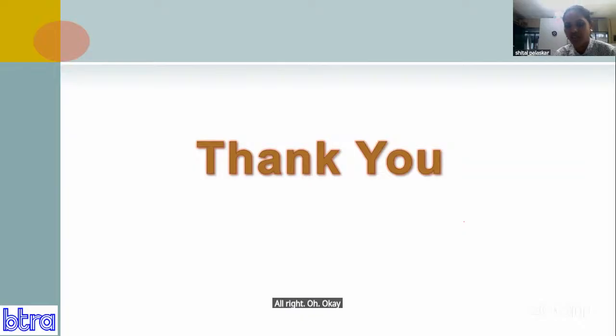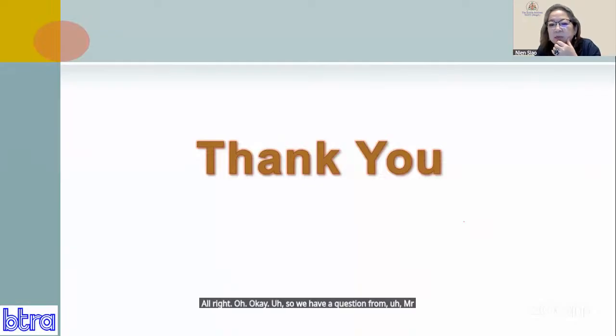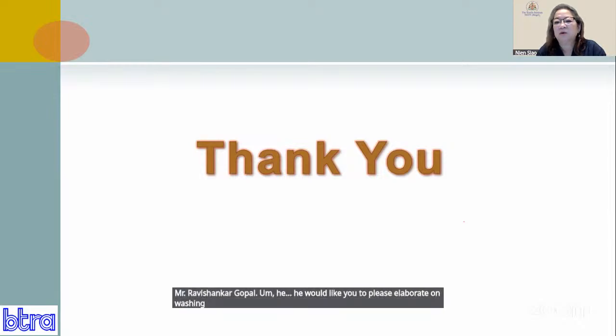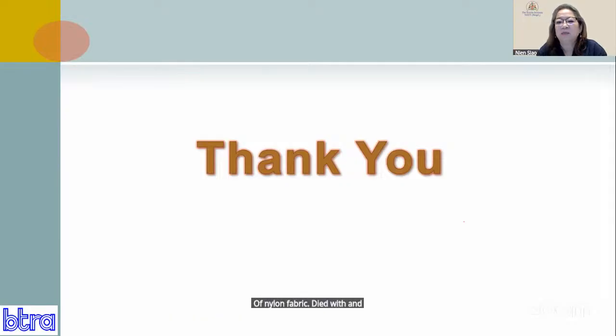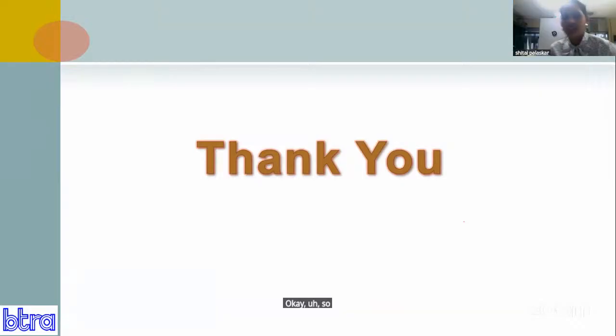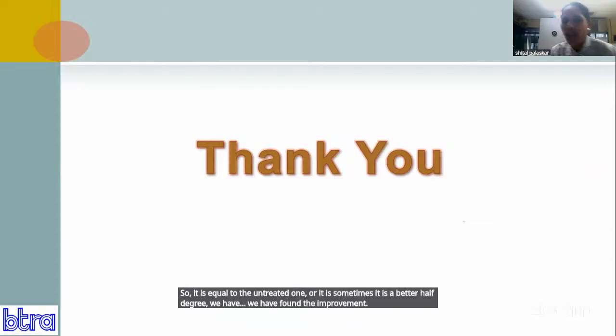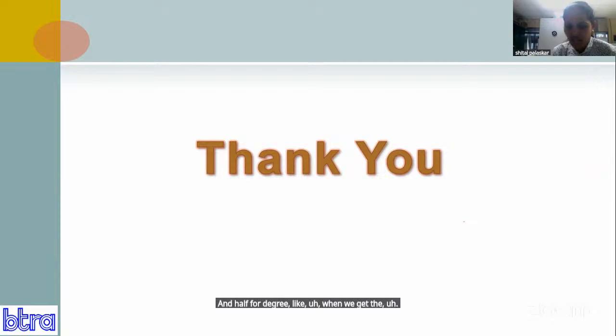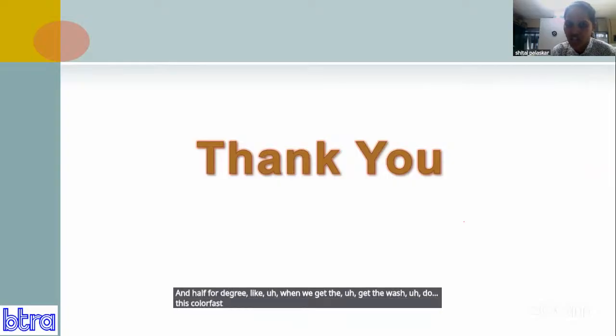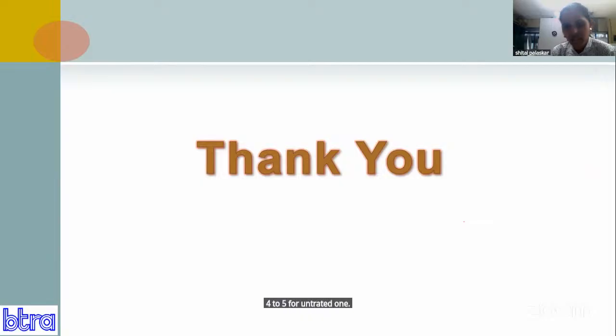Okay. So we have a question from Mr. Ravi Shankar Gopal. He would like you to please elaborate on washing fastness of nylon fabric dyed with and without plasma treatment. Okay, so we have done the dyeing study. Once the dyeing is done, the dye is fixed on the fabric. It is equal to the untreated one, or sometimes better by half a degree. Like when we get a color fastness to washing rating of 4 to 5 for the untreated one, we get the same 5 rating for the treated one. So once it is fixed on the surface, it won't come out after plasma treatment.